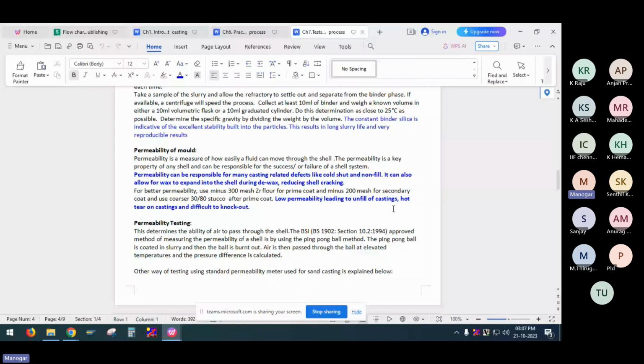And also for removing cold shut and non-fill. It can also allow for wax to expand in the shell during de-wax, reducing the shell crack. So the more the permeability, de-waxing will be easy without any crack.